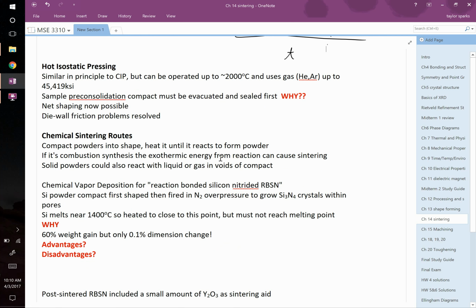They'll use helium or argon because they typically don't want it to react with your sample. And you can go up to just bonkers, right? 45 KSI, 45,000 KSI, that's an enormous pressure, right? So you can apply crazy pressures at crazy high temperatures. This is the gold standard, best way to densify ceramics, right?